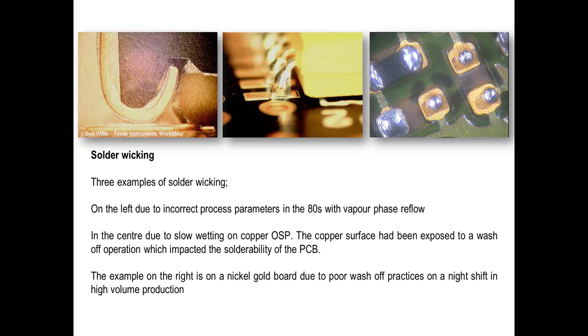Now, solder wicking as a defect can be related to poor solderability of a surface. What you're looking at here is three examples where the pad has not soldered, or the solder has gone away from the pad surface. In these particular situations, it can be the process, i.e. one surface solders quicker than the other, and the opposite surface won't wet within the time the solder is in a liquid state. If you think about this logically, it's pretty obvious.